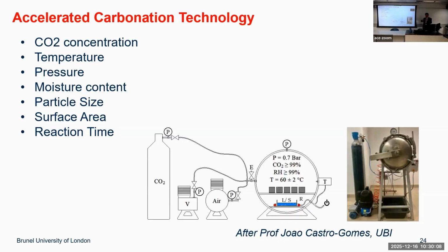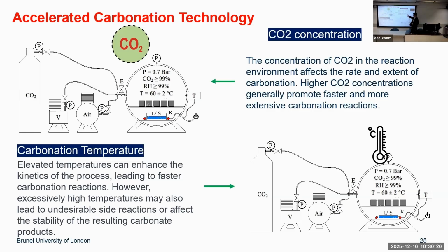Basically, you need the particles to have maximum chance to contain moisture and contact the carbon dioxide, so that you improve the carbonation. Okay, and the concentration is also a factor. In research you use nearly 100% carbon dioxide concentration, but nowadays we move towards around 20% and use flue gas from industrial plants, like cement plants and burning power stations. Generally, with higher carbon concentration you get a higher carbonation rate.